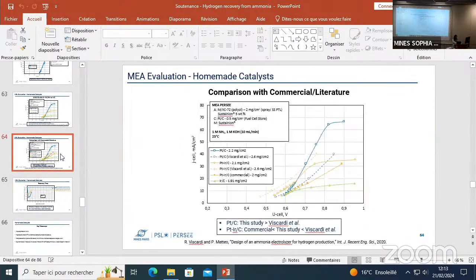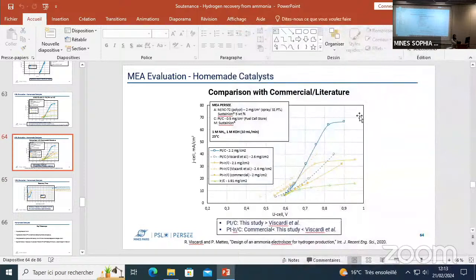But here, if you look at the tests, I was limiting my voltage to well below 1 volt. I'm not really sure how to define high potential and low potential regions, of course. But for me, it was 1 volt because of water oxidation and ammonia. What I see is that below 1 volt and above 1 volt, it didn't really have an impact on the recovery time. But maybe at 0.7, 0.8, I don't know.